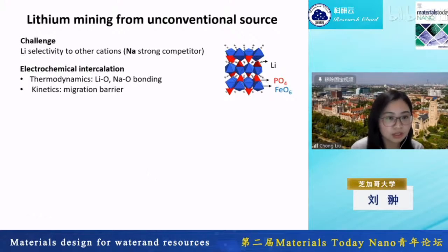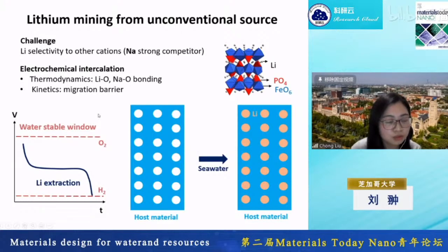So intrinsically, this intercalation reaction can give you selectivity because you have different bonding strengths of lithium to oxygen compared to sodium to oxygen. And also, lithium is much smaller and it has a lower migration energy barrier. So how are you going to do this? So you're going to have a crystal material that's the host structure, and you want to do intercalation. And you first empty the crystal material to have some vacancies or storage sites. And then you put it into the complex environment and you do intercalation.